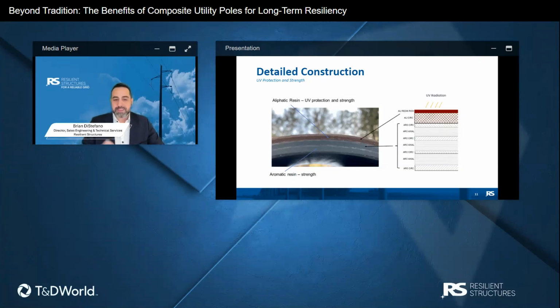You can observe the distinct layers. The gray regions consist of the aromatic polyurethane. That aromatic polyurethane, although it doesn't have great UV resistance, gives the pole its excellent structural integrity and provides the core strength and structure of the pole. And then the outer brown layer gives the pole its final color. But more importantly, that is the aliphatic polyurethane layer. That offers durability and UV resistance, as I mentioned in the prior slide.